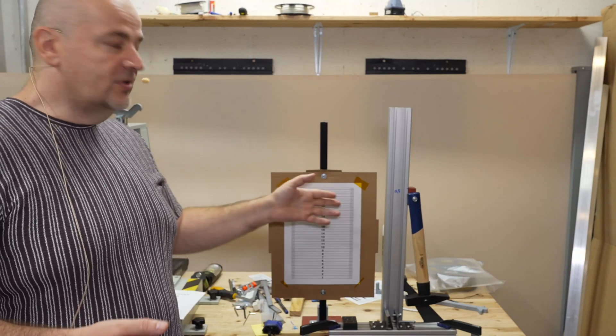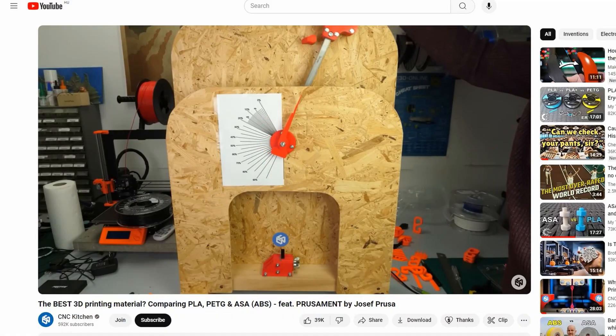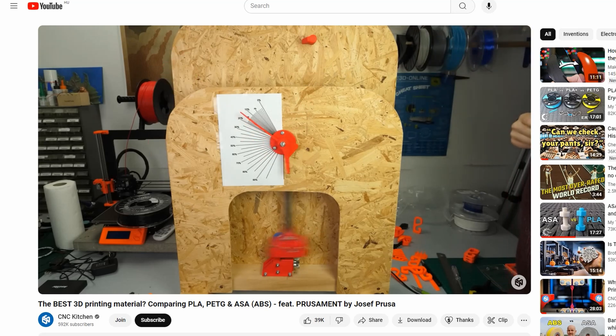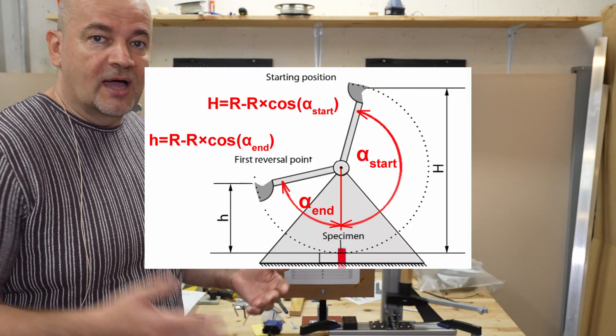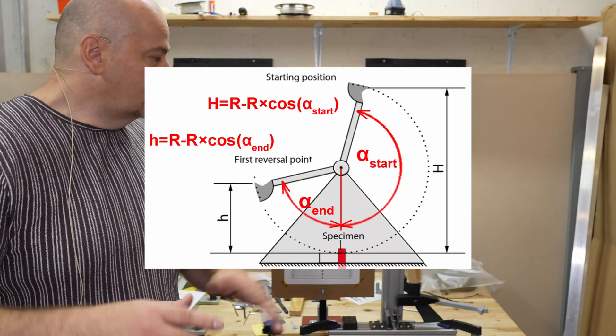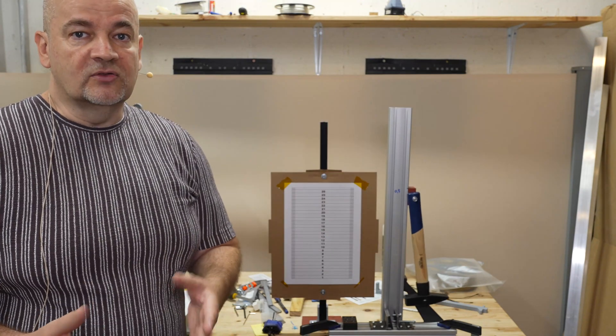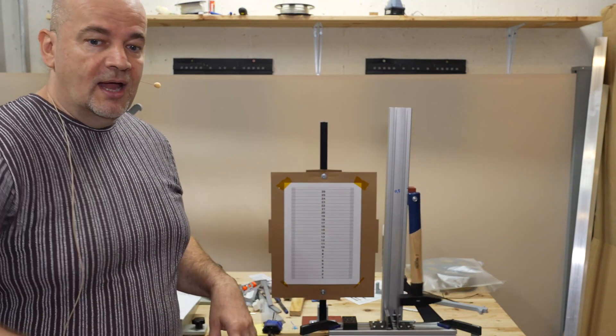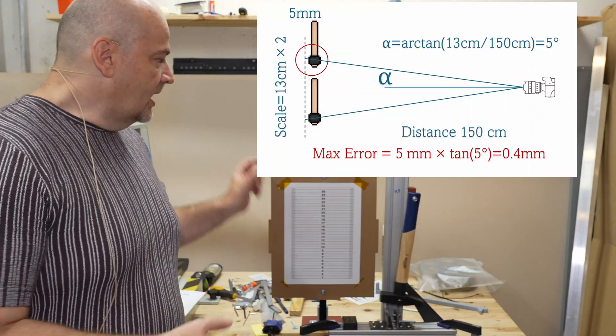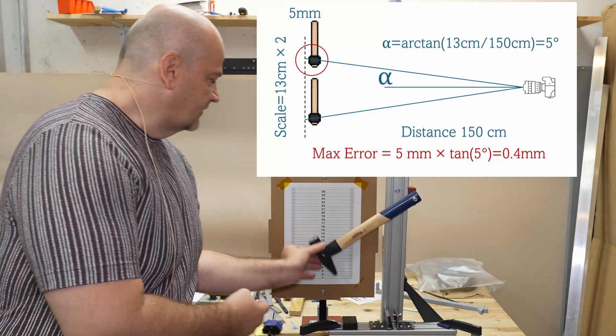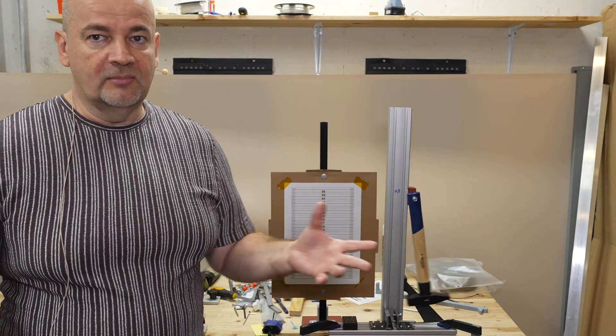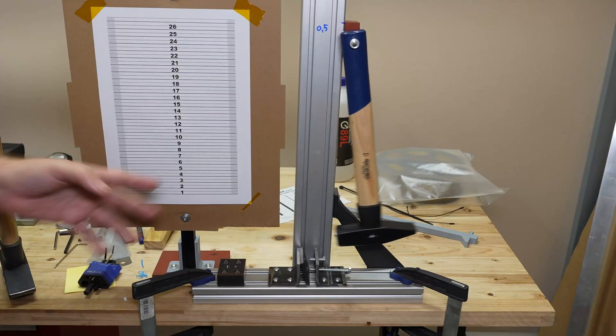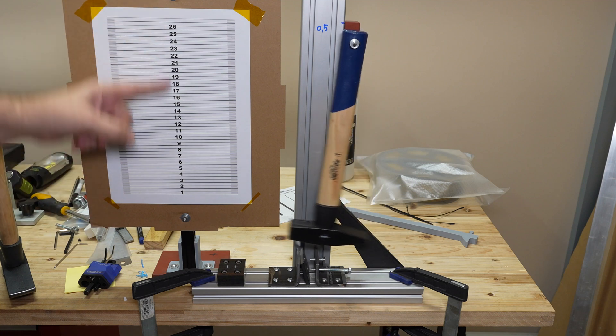Many times I got comments: why don't I measure the angle? Yes, 20 years ago in university I also learned to measure the angle and then calculate the difference in height. But with this I have that middleman. So I'm able with the high-speed camera to measure directly the height, because this is what I need in the calculation. I'm skipping the middleman. I'm placing here approximately one and a half meters. I zoom in and the distance between the hammer and the scale is less than five millimeters, so that parallax error is extremely minimal.